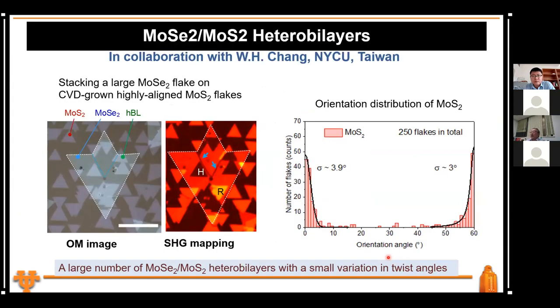So this is work that I have in collaboration with Wen Hao, and for the audience, please keep this part confidential. We are wrapping this paper up, and it should be submitted very soon. This is a paper where I should give the main credit to Wen Hao. He came up with this method that you can use CVD to grow MoS2 highly oriented. The angular distribution is about 3 degrees, okay?